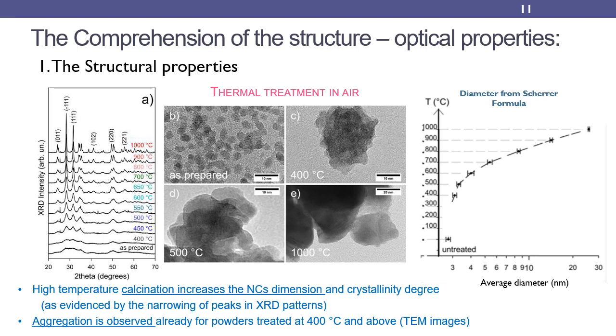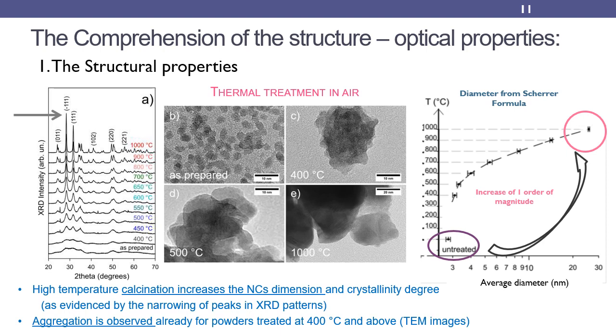The very first characterization of hafnia nanocrystals were performed by XRD and TEM measurements. They both reveal that the obtained nanocrystals have a monoclinic structure and a size of a few nanometers. After annealing the samples, the dimension of the nanocrystals starts to increase up to 30 nanometers for annealing at 1000 Celsius degree. An aggregation of the nanocrystals occurs, maybe due to the removal of organics like benzoate group from the synthesis from the surfaces.